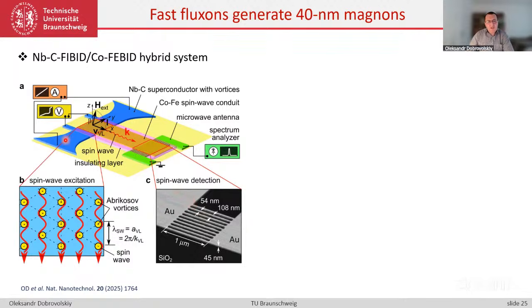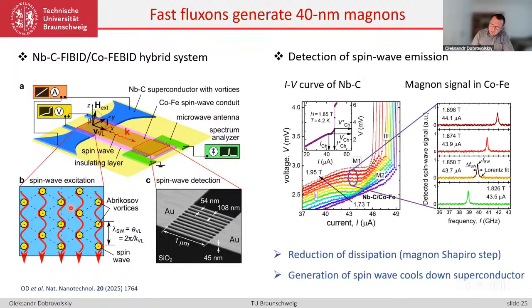I just want to emphasize that we do not apply any AC current to the superconductor. It's only driven by DC current, and the propagation of the vortex lattice in the superconductor itself induces spatial and temporal modulation of the stray field in this hybrid region. And when the matching condition is satisfied, as illustrated here in panel B, then it comes to generation of spin waves. The spin waves can be directly detected by the microwave antenna, as shown here on the right-hand side. And in addition to direct detection of the spin waves by the spectrum analyzer, we also monitor the current voltage curve of the superconductor.